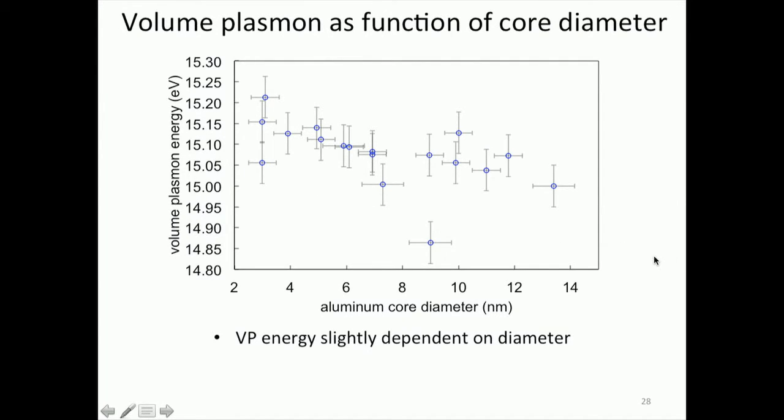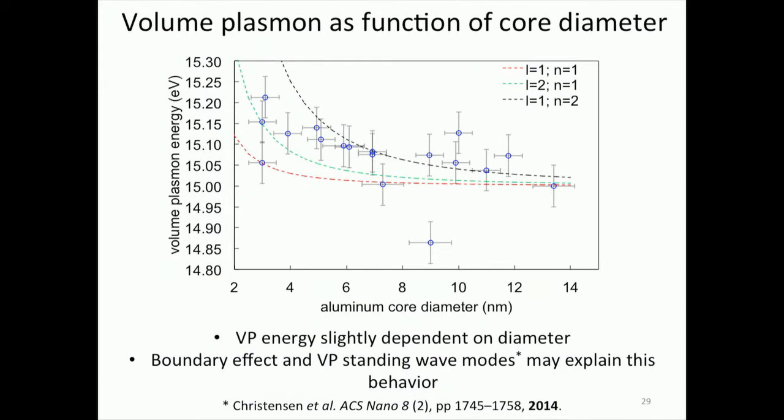It is slightly dependent on diameter. In order to try to understand this data set, we performed a simulation based on this paper, which studies the non-local volume plasmon modes. They also study the higher order volume plasmon modes in nanostructures. Basically, the core of the simulation is that you have to consider the volume plasmons as standing waves inside the diameter, and they provide relationships of different volume plasmons with different wave vectors.